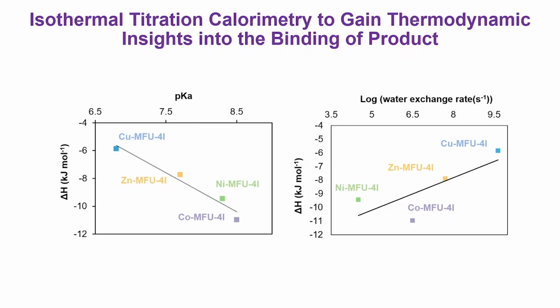But if we take this plot here, this is telling us that the cobalt and the copper like to bind water really strongly, but even when the substrate competes for that active site, they like to bind the product very strongly. That means the substrate will have a hard time binding. The zinc is somewhere in between, which means once you reach a certain concentration of the product, now the substrate will have a hard time binding, and maybe that's why it plateaus around 90%.